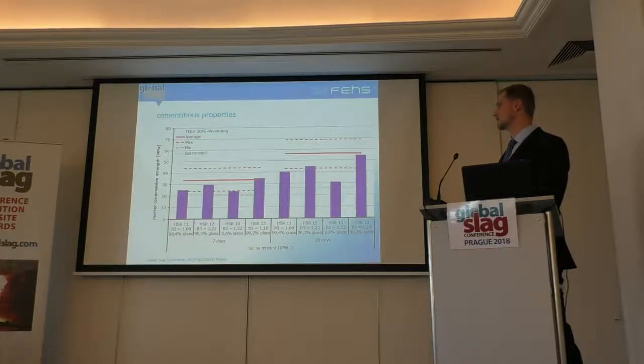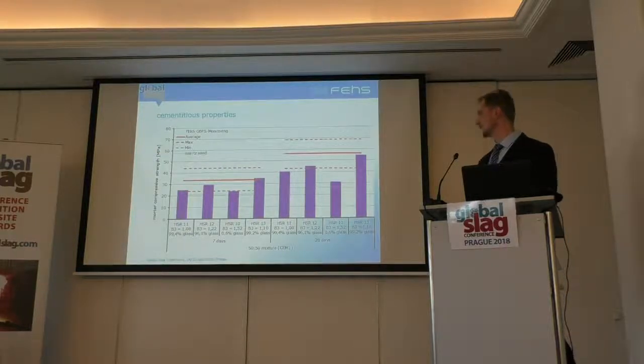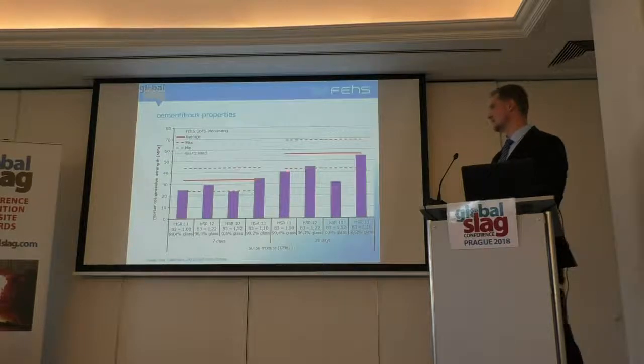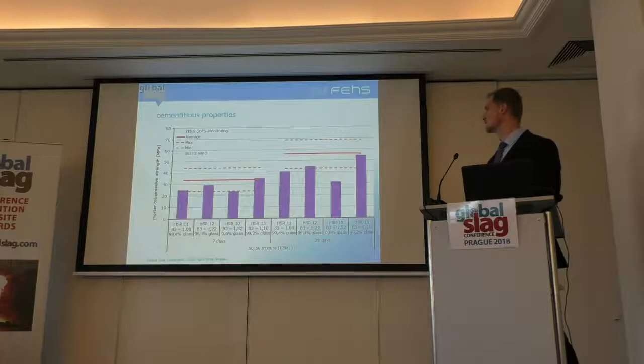With the first trial, where we got a very low B1 basicity, the compressive strength is very low. It's at or below the minimum, also after 28 days. After increasing it, we are in the range of the minimum, that is like a very bad